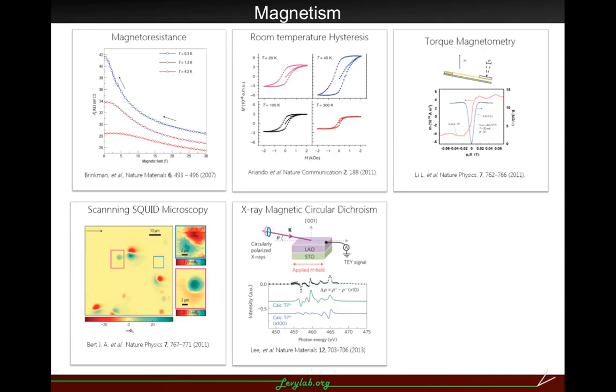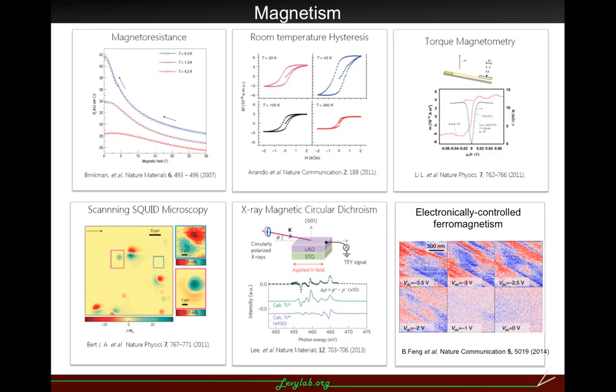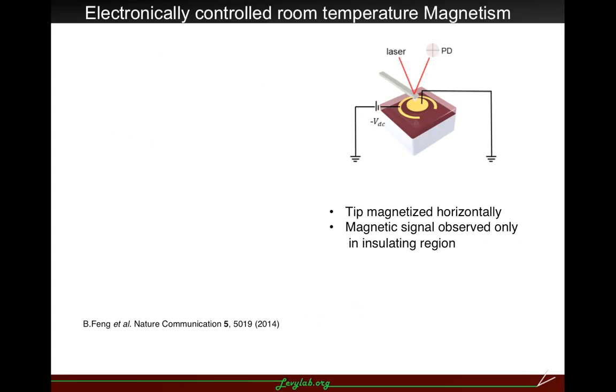The origin of magnetism has also been studied. By X-ray magnetic circular dichroism and X-ray absorption spectroscopy, they found this in-plane magnetic order is related to titanium 3d character of the dxy orbital in an anisotropic t2g band. Electronically controlled ferromagnetism has also been studied at room temperature.